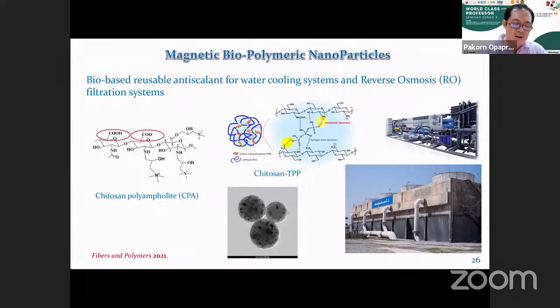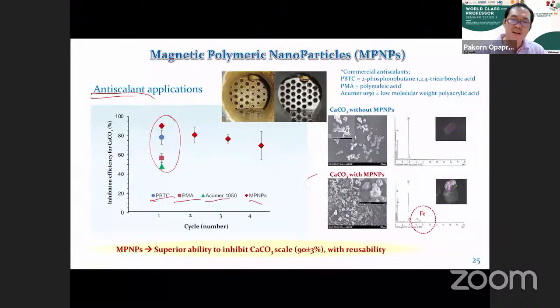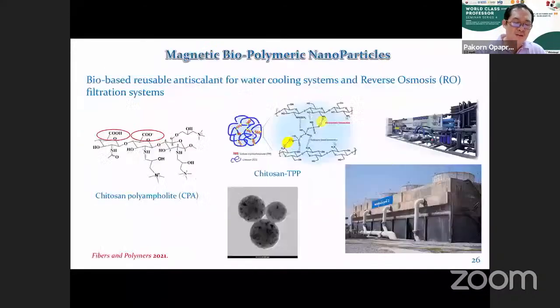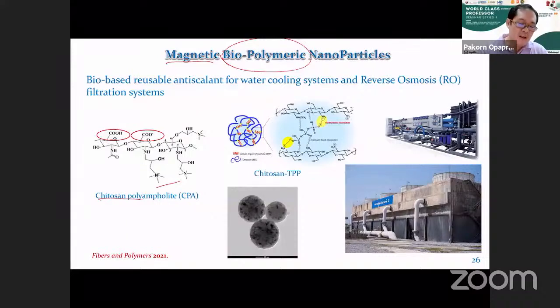We are also now working on another type, because this material is made from polystyrene-co-acrylic acid, which may not be friendly to the environment. So we want to move further to polymers that are bio-based and can also be degraded after use. We have a collaboration with Professor Fitri here, and we developed a system of chitosan copolymer that has positive and negative charges in the structure, and we can incorporate this with the magnetic nanoparticles to make similar materials that can perform in the same way but are more friendly to the environment. So this work is also ongoing, and it has high potential for commercial use.